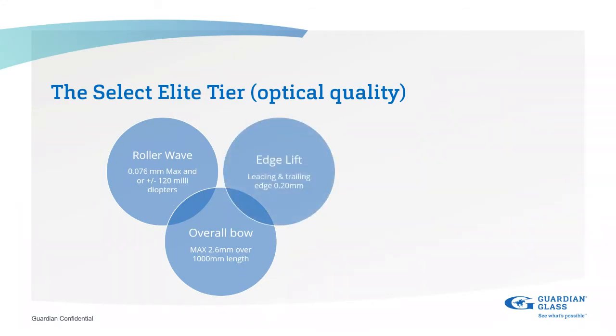Edge lift, leading and trailing, obviously, this is something else that becomes more apparent. The international standard there stipulates 0.5. We're looking at reducing this to 0.20 millimeter, to reduce the effect of the leading edge and trailing edge distortions.